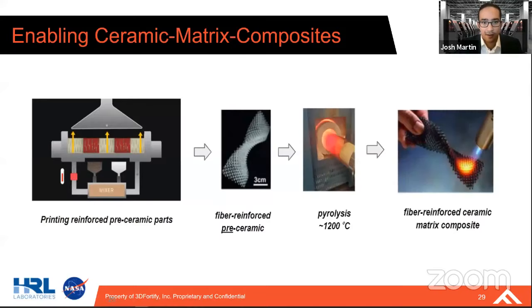And this is a different type of polymer. In this case, we're using a pre-ceramic that's in partnership with HRL Labs. The unique piece here is that these polymers, which are photosensitive, can be run through pyrolysis up to 1200 degrees C, and they essentially degrade into a ceramic matrix. And so we're able to take the very same platform that we use to print fiber reinforced polymers and use that to print fiber reinforced ceramic matrices.